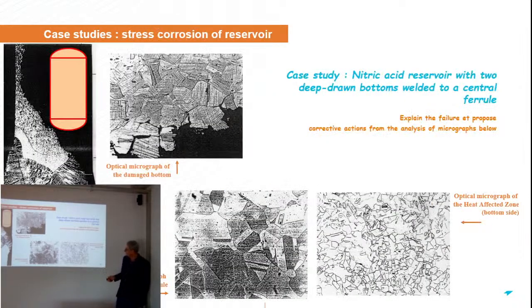This is the first example I wanted to show you. This is a case study we do with our students, which is the case of a nitric acid reservoir with two deep drawn bottoms and a central ferrule here. And you can see here the damage of the bottom of the reservoir. You can see here the welding between the ferrule and the bottom. And you can see here the material, which is stainless steel, very typical microstructure of the stainless steel. This is an optical micrograph, and here you have the damaged part, which is somewhere here.